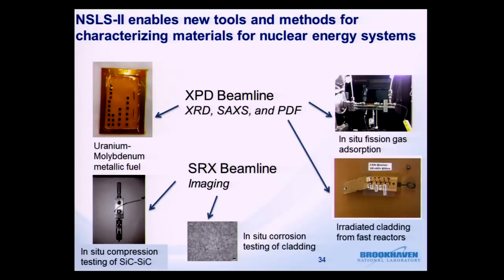So the sample is in here. There's a load cell, and we put the sample under compression at the beamline and watch the crack grow, take images of it. I discussed the in situ corrosion testing of the clad. We've also been looking at irradiated samples of other types of materials that could be used for cladding. And these are mainly the advanced steels. And we're doing very similar experiments to the steel that I described for the reactor pressure vessel. We're looking for defects created in the material from the damage. We'd like to do that with XRD and SAXS at the XPD beamline.